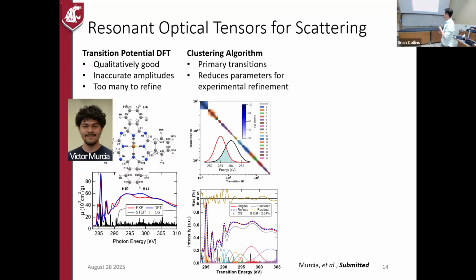This is using an amplitude overlap type of algorithm where we cluster based on overlap of the amplitudes. This is a matrix of those overlaps, with one transition overlapping with another. Of course, on the diagonal they all overlap with each other perfectly, and as you get further away, they overlap with each other less and less. We use that to cluster these into different specific primary clusters, which are shown down here, the result of that clustering algorithm.